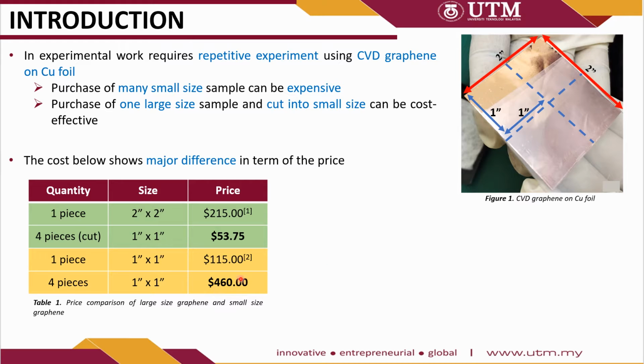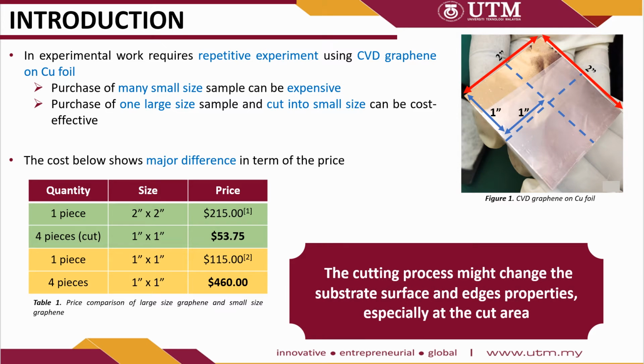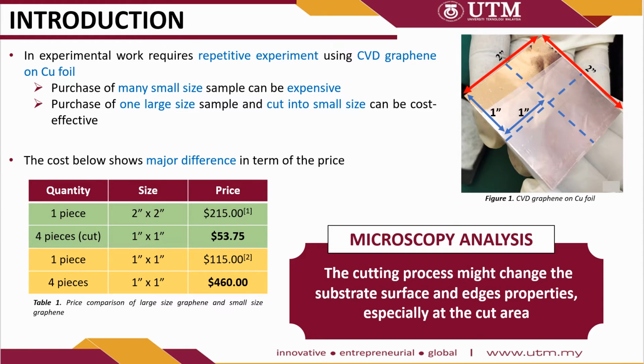However, it is important to note that the cutting process might change the substrate surface and edge properties, especially at the cut area. Therefore, microscopy analysis is important for surface evaluation on copper foil substrate grown with single-layer graphene prior to further experimental work.